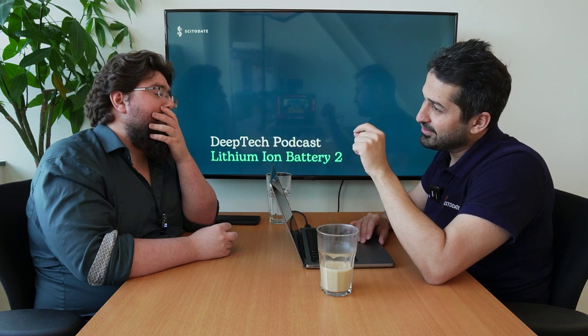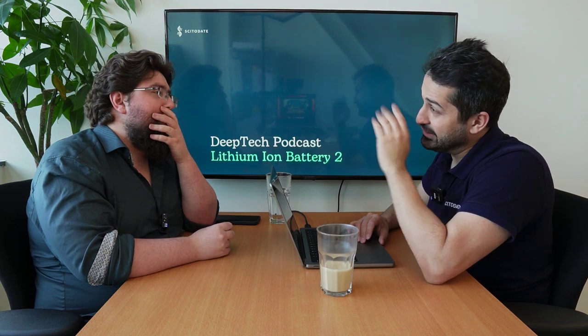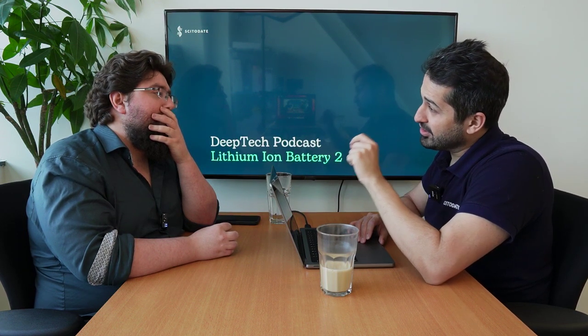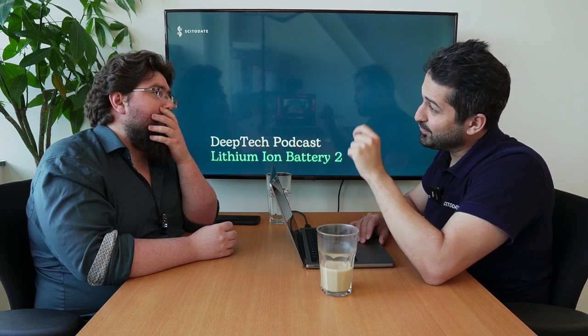There is another thing that makes it very good: there is a big difference in energy, electrochemical energy, or the ramp is quite steep for cobalt oxide with lithium and without lithium. The energy difference of these two states of material is quite high. So it's reversible, but it's high. So when you snap out the lithium from it, it takes quite a lot of energy to take the lithium out, and it gives a lot of energy back if you put the lithium in. But still stable.